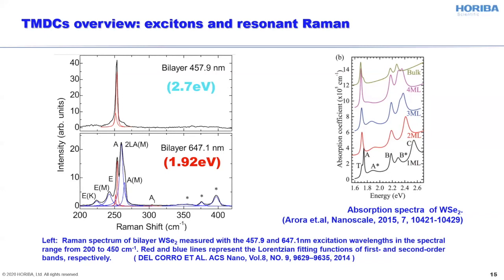And in this slide, you can see a comparison of the same sample probed with non-resonant excitation at 2.7 eV and resonant excitation with red. With resonant excitation, we can see many more peaks. And this makes our life more interesting and more difficult at the same time, because interpreting all those peaks that we observe with resonant Raman sometimes becomes challenging, but having this wealth of information and the choice whether we can do resonant or non-resonant excitation is a great advantage for characterization of these materials.